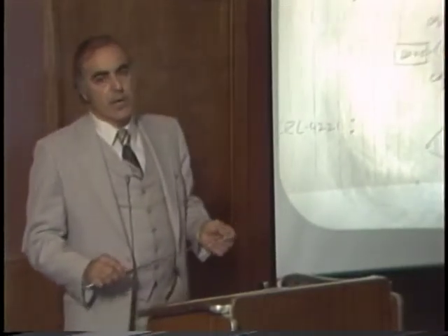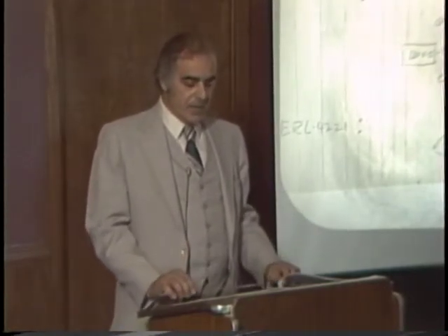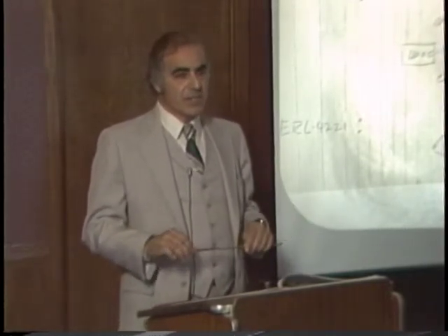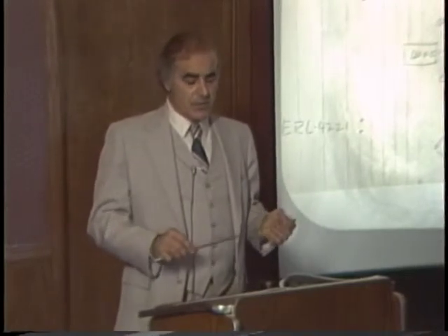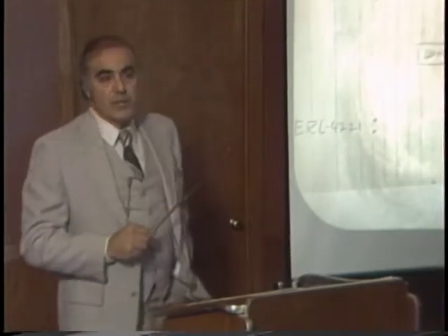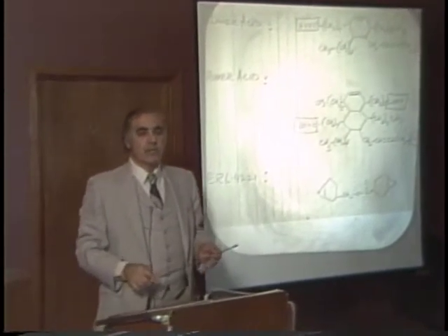In looking at polymer crosslink density, we looked at a system that was selected because we could vary the crosslink density without chemically modifying the system to the point where it could influence the results. And what I'm showing here is a slide of the structures of the materials that we're using. A dimer acid, which is difunctional in carboxylic acid functionality, trimer acid, which is trifunctional in carboxylic acid functionality, and ERL 4221, which is the diepoxide that we use to link the whole system together. If I may have the next slide, please.